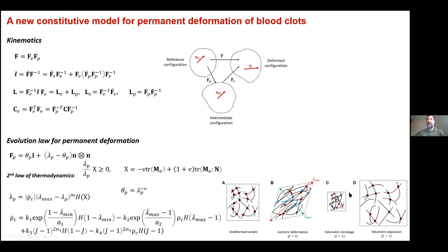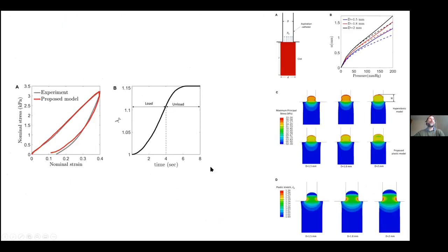And the same if we try and compact the network. We're pushing all the fibers closer to each other, and we get formation of new crossbridges or crosslinks between different strands of fiber. So we've developed a thermodynamically based model where we have a kinetic equation describing the rate of bond formation and the rate of bond breakage also. And when we compare it to an experiment where a clot is stretched and then released, and it doesn't go back to its original position, our model is giving a very good prediction of this.